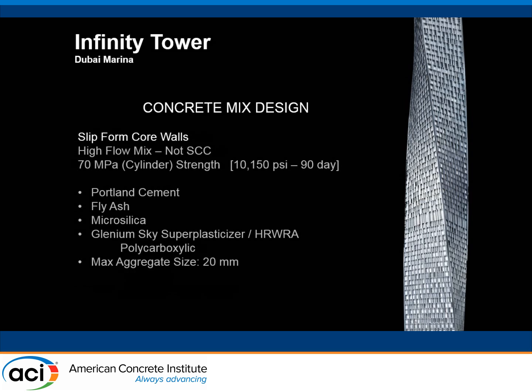The core walls, the central core walls, were a bit of a unique thing. They actually slip formed the core walls. They had slip forming technology out there, and they were advancing the core walls through slip forming, and they were going way ahead of the rest of the tower. We actually had to tell them they had to put the brakes on after a while because they were going way beyond what they were able to keep up with the rest of the frame.